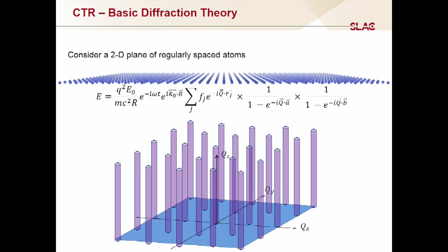And so going from one of these halfway to the next one, I'm going to not see any intensity. But if I'm looking along the z direction, it's actually continuous scattering. Okay, so basically what this means is that something that is well-defined and isolated in real space leads to a very extended feature in reciprocal space, and vice versa.